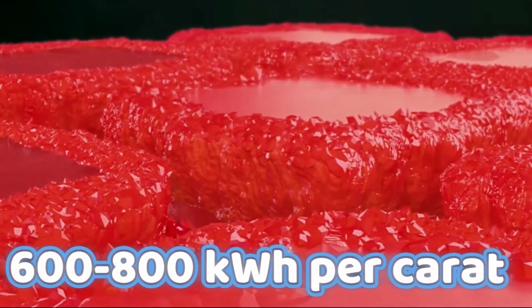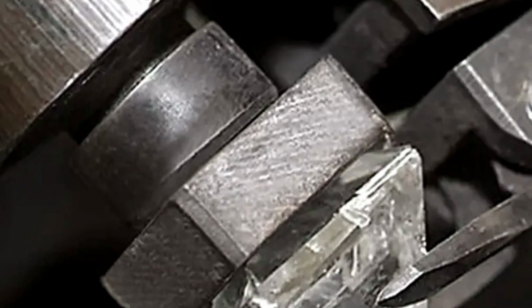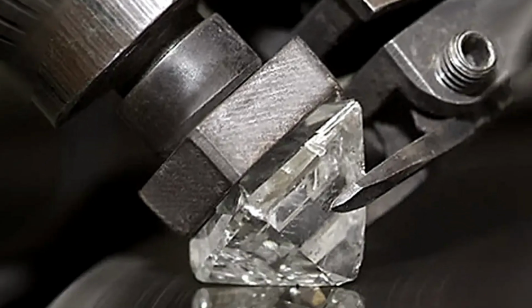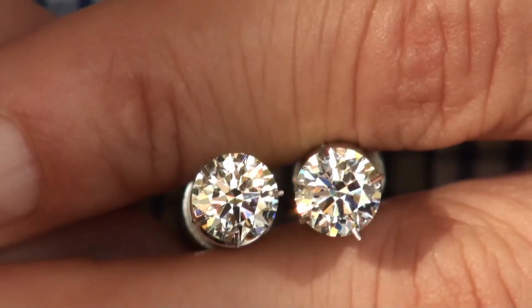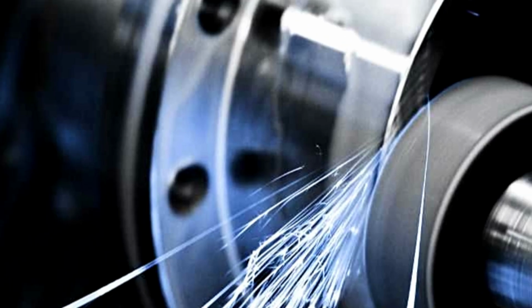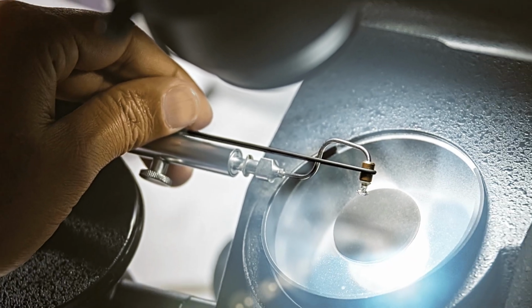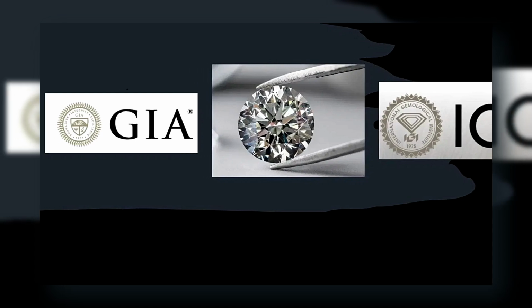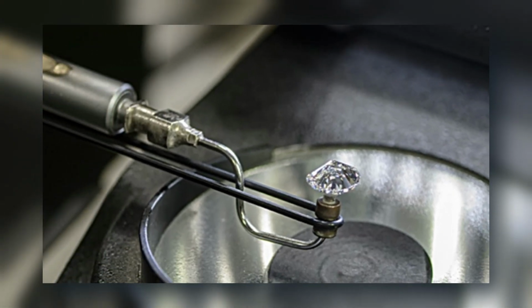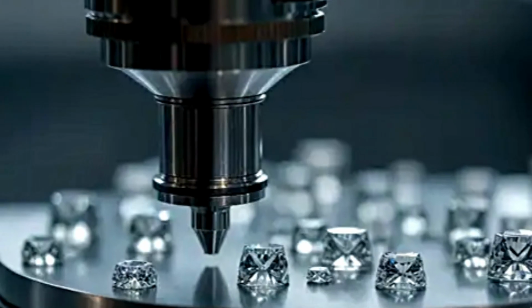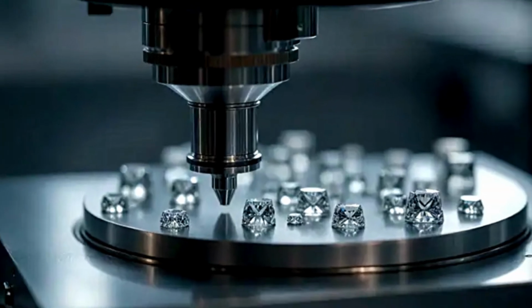The CVD process, for instance, consumes about 600 to 800 kilowatt hours per carat, comparable to household energy use, and produces no mining-related waste. HPHT, while more energy-intensive, is still far less destructive than mining. These diamonds are also 20 to 40% more affordable, making 99% pure gems accessible to a broader audience. Gemological institutes like the GIA or IGI grade them identically to mined diamonds, evaluating cut, color, clarity, and carat, ensuring they're indistinguishable even under a jeweler's loupe.